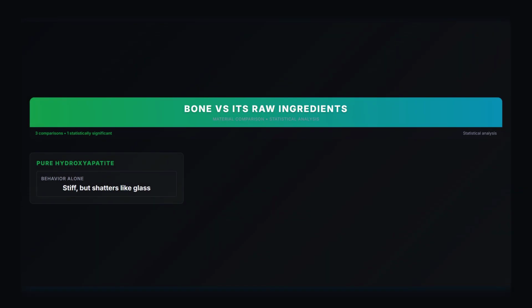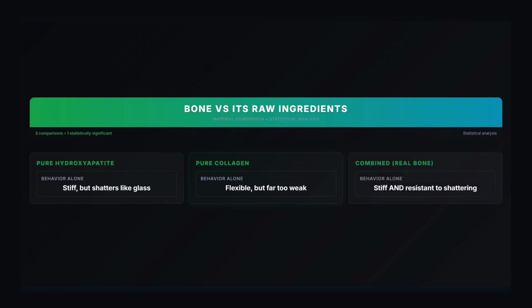Adult cortical bone, the dense outer shell of your bones, typically has a stiffness, or Young's modulus, around 15 to 20 gigapascals, and can withstand roughly 100 to 200 megapascals of compressive stress before failing. Those numbers will matter once we start changing the speed of loading. It helps to compare bone to materials engineers actually understand well. Pure hydroxyapatite mineral, on its own, is stiff but shatters like glass. Pure collagen protein, on its own, is flexible but far too weak to hold up your skeleton. Combined, bone lands somewhere far tougher than either ingredient alone, which is the whole trick.